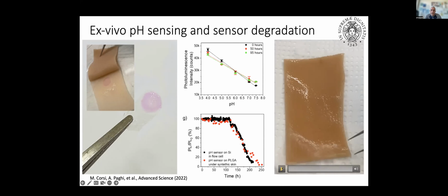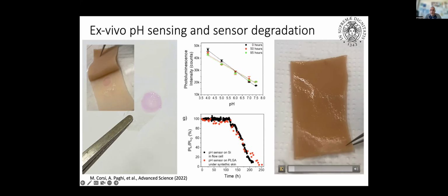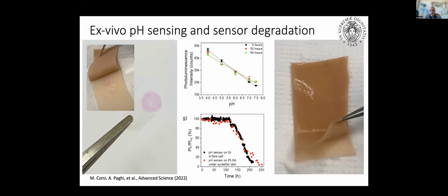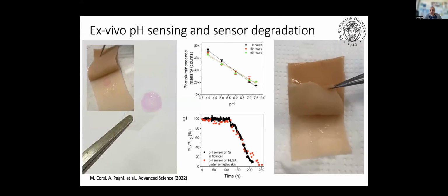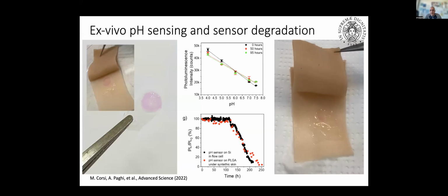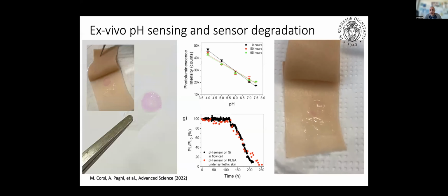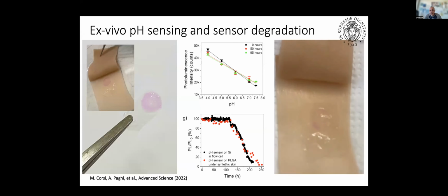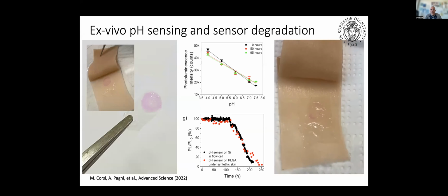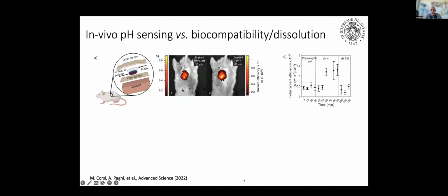Here you see after the experiment, after 4 days, you lift up the upper layer of the skin, and you see that you just find the PLGA, and the sensor, the porous silicon sensor, almost disappeared. So this is nice, but then we have to go in vivo. We went in vivo. We did several experiments with an animal model.